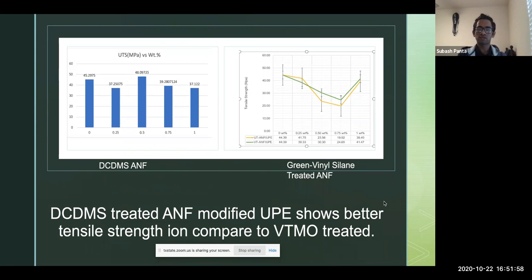So if we compare the tensile strength of dichlorodimethyl silane treated versus vinyl silane treated, dichlorodimethyl silane treated alumina nanofiber modified polyester shows better tensile strength properties compared to vinyl silane treated alumina nanofiber. In terms of vinyl silane treated alumina nanofiber, the maximum tensile strength obtained was 38 megapascal at 0.25 weight percentage. Similarly, at 0.50 weight percentage it is 30 megapascal, at 0.75 weight percentage 24 megapascal, and at 1 weight percentage 41 megapascal. So the vinyl treated aluminum nanofiber didn't show proper tensile properties.